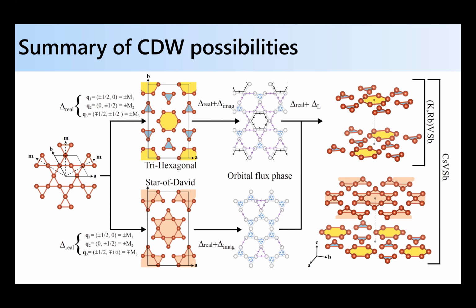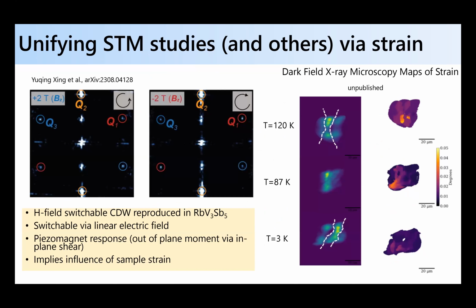I think in terms of the strongest evidence that something weird is going on, I would say the STM evidence. It's hard to get around that the charge density wave state is coupling to a magnetic field, in which case, at least I don't know of another way of doing it without breaking time reversal symmetry. So with magnetic field, what really happens in STM? Yeah, so, well, Vidya can correct me if I'm wrong, but you basically survey a surface, and then they Fourier transform it, and they see the charge superlattice peaks. And those are along 3 different Qs, which nominally can be inequivalent. And so they see inequivalent spectral weight at the 3 different Qs. But they can flip the winding of that with the application of a magnetic field.